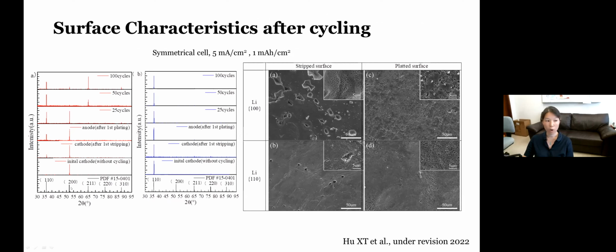For the lithium 100, it still evolves, eventually to a dominance of the 110 diffractions, but eventually the 211 also grows. But in the case of the lithium 110 sample, you see this prevalence of the 110 diffraction always lasts towards the end. And in terms of the surface morphologies, similar results are observed. But even for lithium 110, you see a little bit of pitting start to occur at high current densities. But the density is a lot lower compared to the lithium 100.